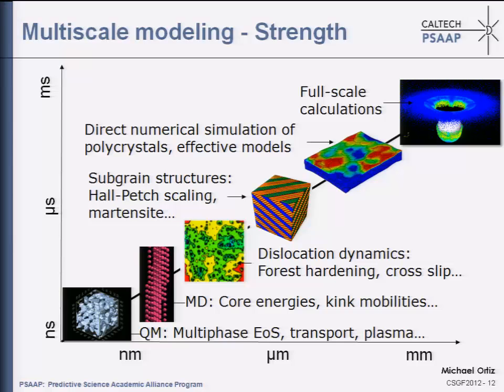You begin to see maybe kinks in the dislocation line, and you can start using atomistic models to compute basic properties, such as core energies or kink mobilities, that give you the behavior of the material at this level. There are also many material properties that can be computed at the quantum mechanical level, such as equation of state, maybe some transport properties, and as I was saying, you can calculate them from quantum mechanical calculations. So here you have a typical hierarchical structure for, say, modeling strength in a metal.